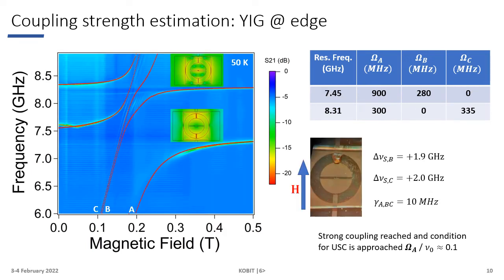We moved the sample in the same orientation with respect to the applied magnetic field and repeated the same measurement and the same analysis, and we obtained similar results to the previous position. In this case, just two different magnetic modes coupled to the photonic modes. Besides the strong coupling in both positions, the high-order magnetostatic modes are also excited.